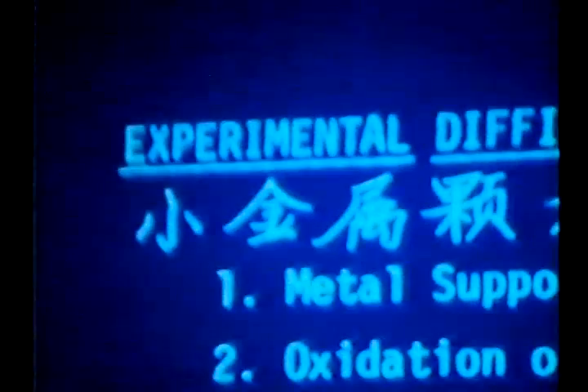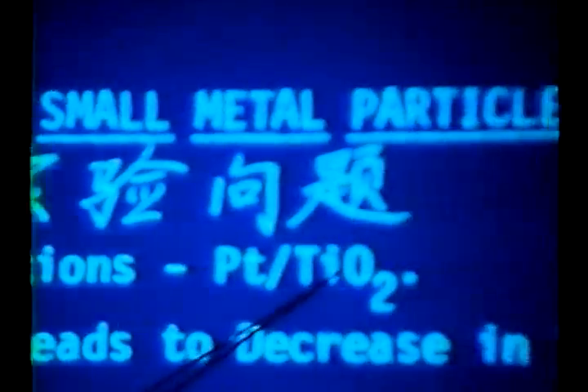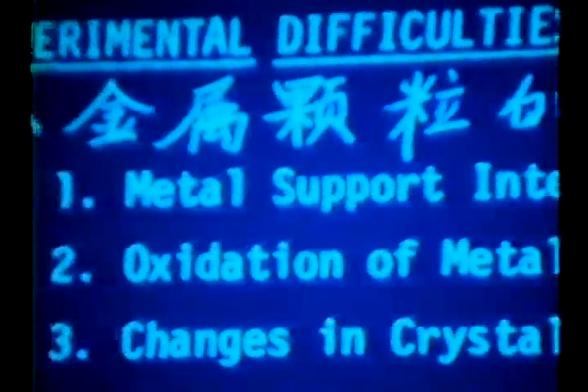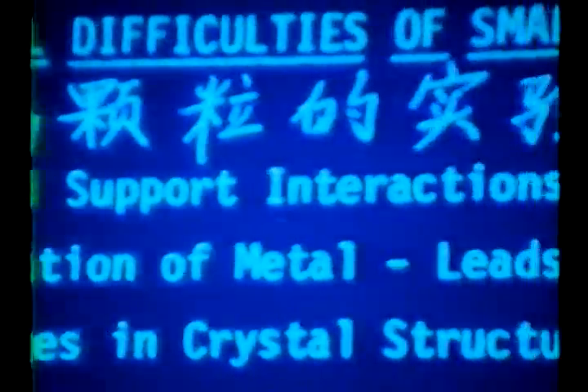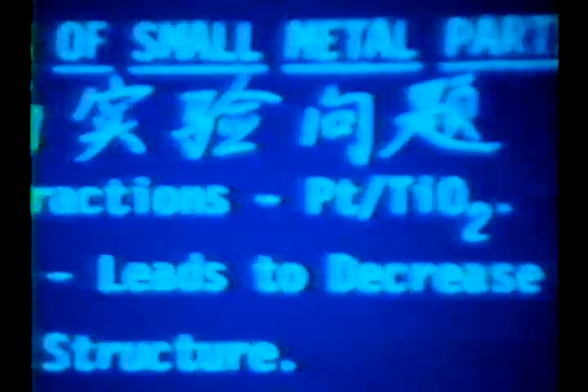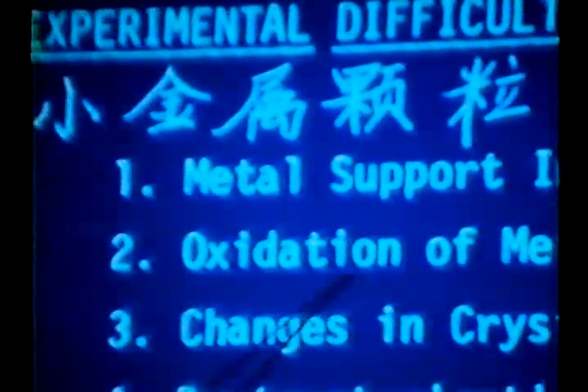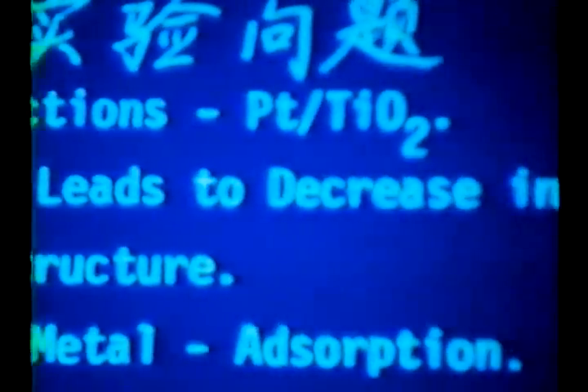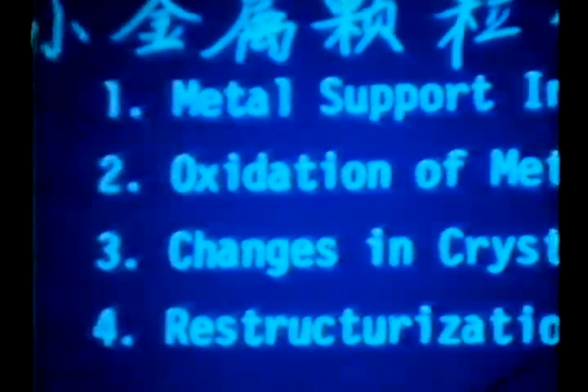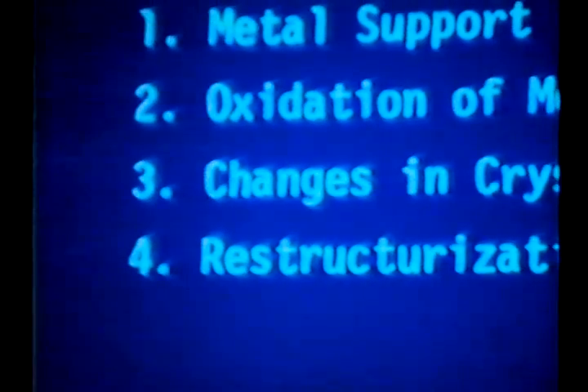But what are some of the problems of making small metal particles and trying to trap them inside the zeolite? First of all, there's been a lot of work in this area recently, strong metal support interactions, where a support like titanium can creep up around the platinum and cover over the platinum, decreasing the surface area on the platinum. Another problem is oxidation of the metal. These small metal particles are usually very active. They like to oxidize very readily. That can lead to a decrease in the turnover frequency rate in the reaction.